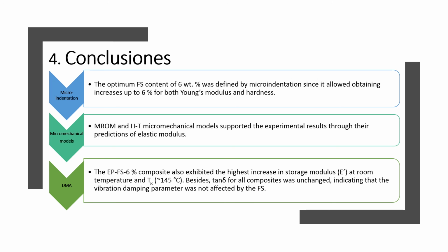Through the results that were obtained, the following final remarks can be stated. The optimum content of ferrotitaniferous sands of 6% in weight was defined by microindentation, since it allowed obtaining increases up to 6% for both Young's modulus and hardness. Both micromechanical models, the modified rule of mixture and the Halpin-Tsai models, supported the experimental results through their predictions of elastic modulus.